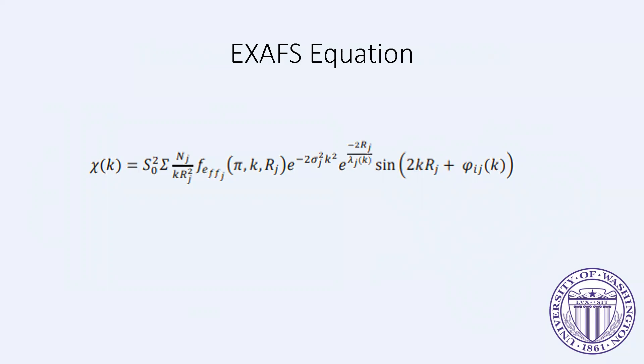Another exponential term accounts for the losses due to any inelastic scattering. The oscillations in the EXAFS spectrum are reflected in the sinusoidal term, where φ(i,j,K) is the ab initio phase function for the shell j, and S₀² is an amplitude reduction factor.